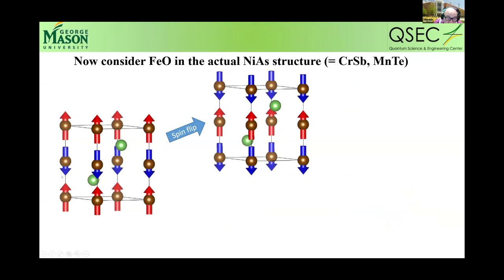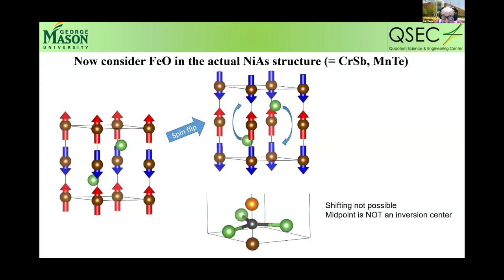There is a symmetry operation, definitely, which maps one sublattice onto the other, but it's not a shift. If I try to shift, then of course my green atoms end up in the wrong positions. And the midpoint is not an inversion center, as you can clearly see, again, in the same sketch. It's a mirror, a very simple mirror, but there are also other symmetry operations like glides or screws, but a simple mirror does it.